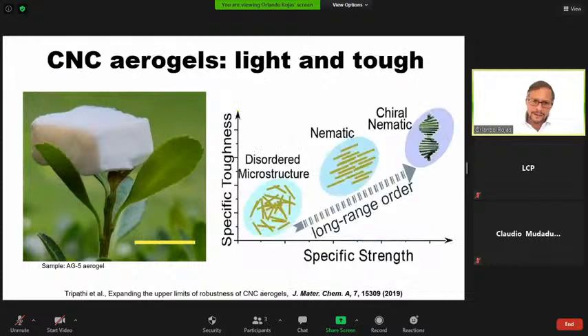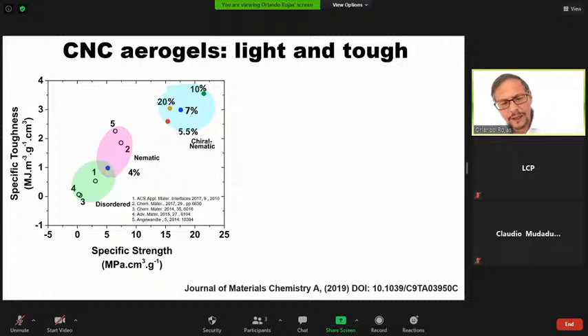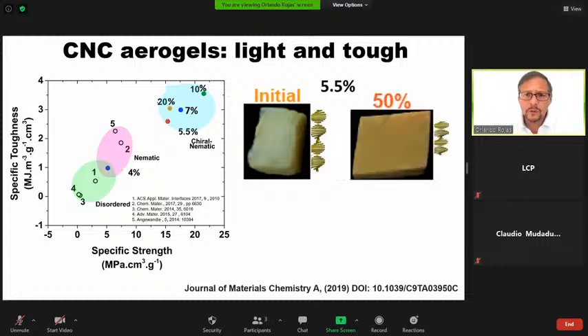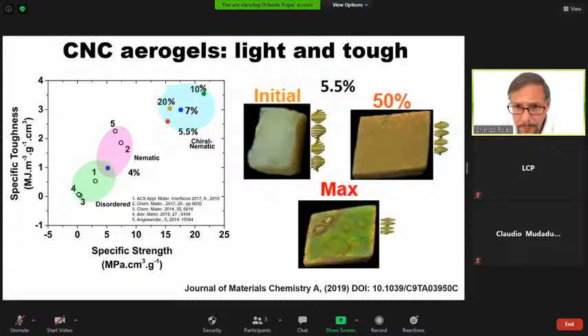And the idea here, as you follow the specific toughness against the specific strength, is that when we structure the material from disorder to oriented or nematic to chiral nematic, that is the one that I introduced earlier, then we have an increase in both strength and toughness. And for that very reason, here we see the results of the same map for our materials that you see in the blue cloud there. Very interesting. But another thing that we observed that is also quite appealing is that these materials not only are strong, but are also optomechanically responsive, meaning that if we take the material and we compress it, it will change the color. And that can be very interesting for many applications related to strength and signaling the load of a material in a composite or in advanced materials.